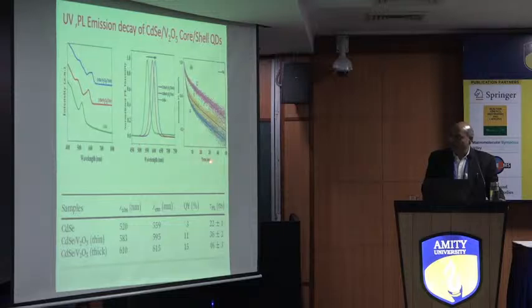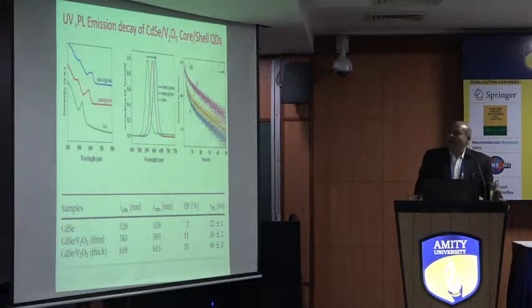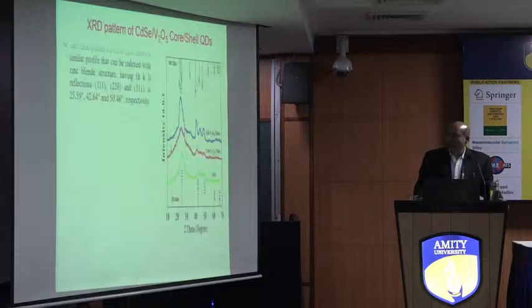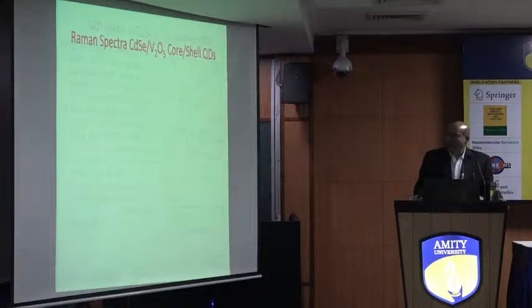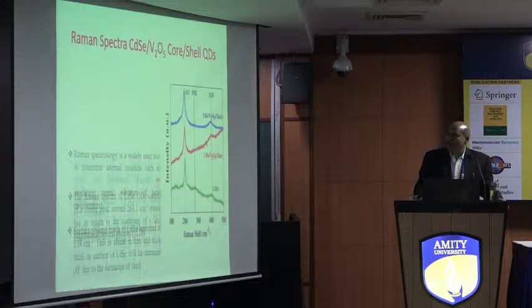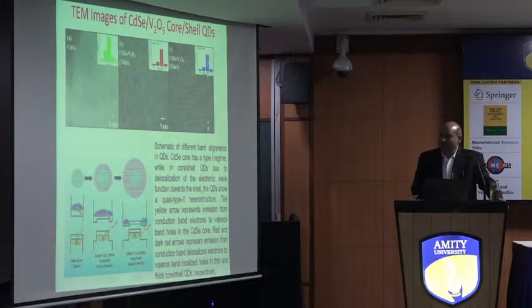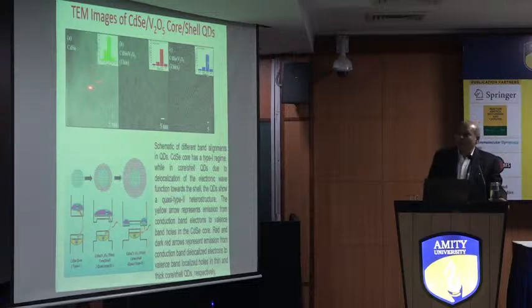Then we take femtosecond measurements. Then we calculate the quantum yield. The quantum yield also increases with the shelling of ZnS on the CdSe quantum dot. And I want to show you, this is the XRD showing a hexagonal structure, and the Raman spectrum is okay. This is the TEM image, for pure CdSe, then CdSe/ZnS, about 3 nanometers, 4.5, then 6 nanometers is coming here.